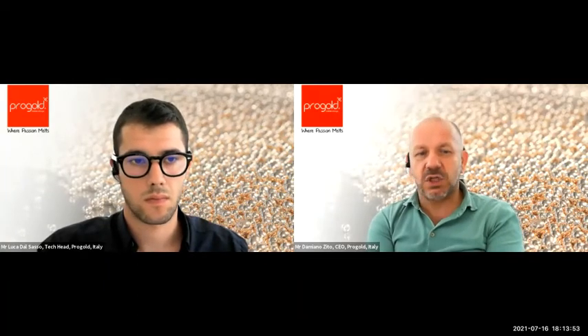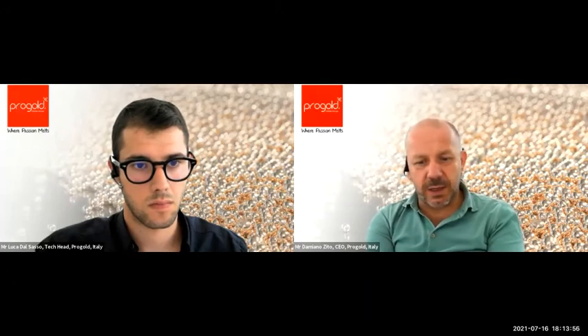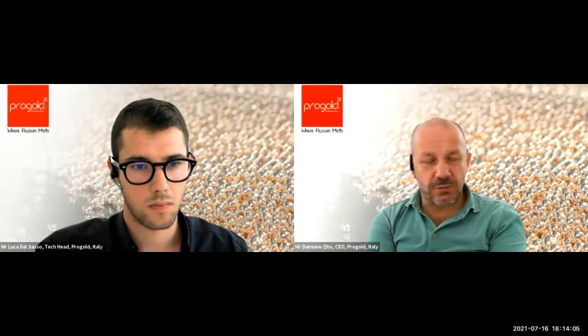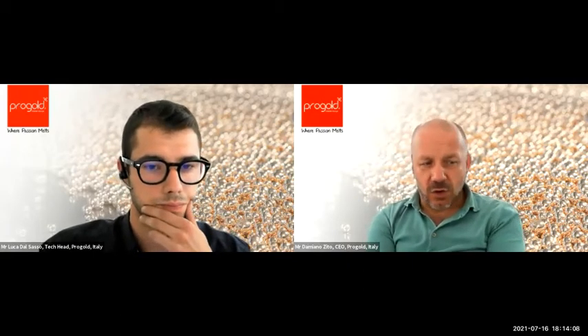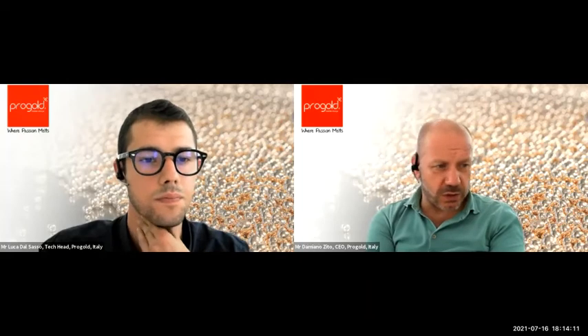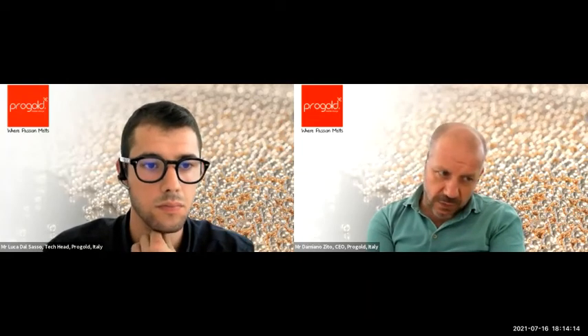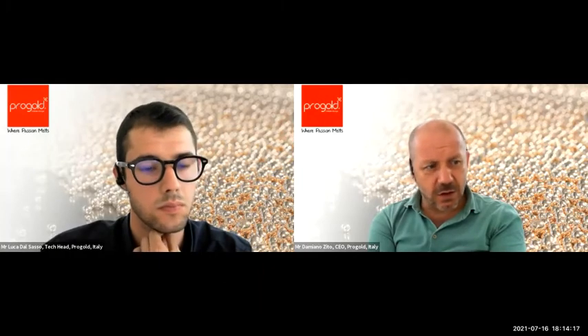It depends from the composition of the hard spots that sometimes could be pollution coming from the pure gold, and sometimes could be the abrasive entrapped in the surface of the metal. But in that case, we need the electronic microscope to distinguish between if the hard spot is a cluster of grain refiner in the alloy, or pollution, or abrasive inclusions. So in that case, potentially yes is the answer, but if the alloy work well, it should be not the reason or the source.